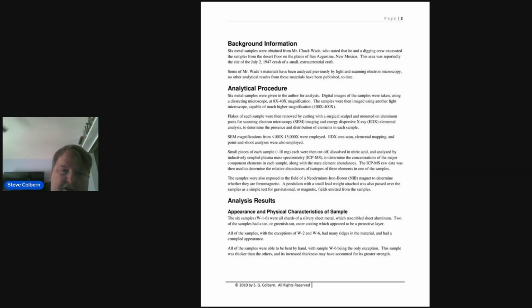The analytical procedure was that I did low and high power light microscopy on all the samples, and then cut small flakes of each material off to do SEM. We did SEM and EDX mapping and point-and-shoot techniques, and then I cut about a 10 milligram piece off of each sample and sent them in for ICP-MS, inductively coupled plasma mass spectrometry analysis. That's a technique where you dissolve the sample in nitric acid and send the liquid through a plasma torch and then through a mass spec.